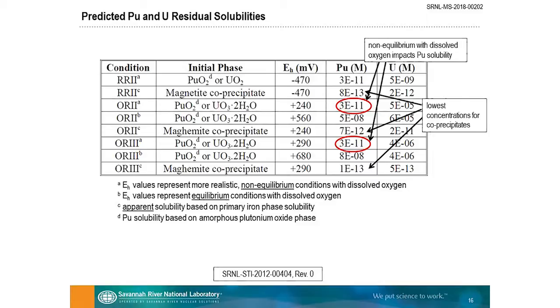I'll just tell you that they kind of looked at 3 cases. One where you're assuming a phase, and you're assuming that for the oxidizing cases, the sample is in equilibrium with dissolved oxygen. Well, that's not necessarily a case that you can achieve readily. There's kinetic limitations on that. So they also looked at cases where you did not have equilibrium with dissolved oxygen.